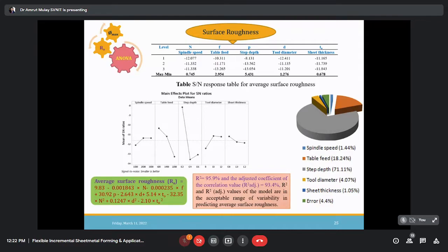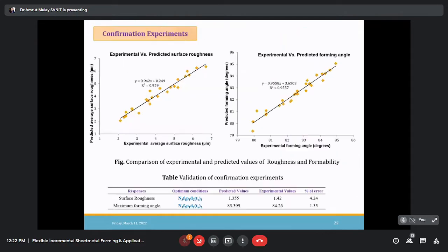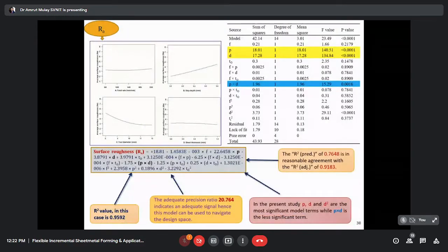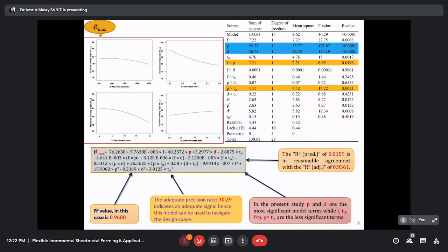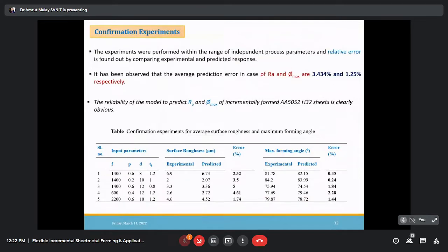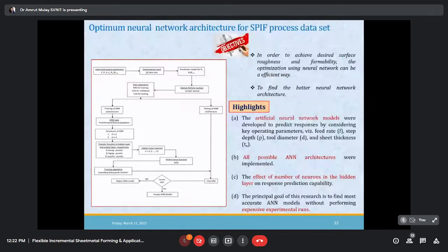So this is nothing but the process is evolving. Now we do not consider that, and using the Box-Behnken method, we again found the empirical relation for the surface roughness and maximum forming angle, and we had some confirmation tests, and we found the error.